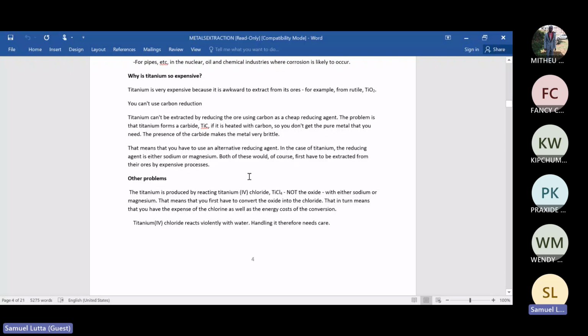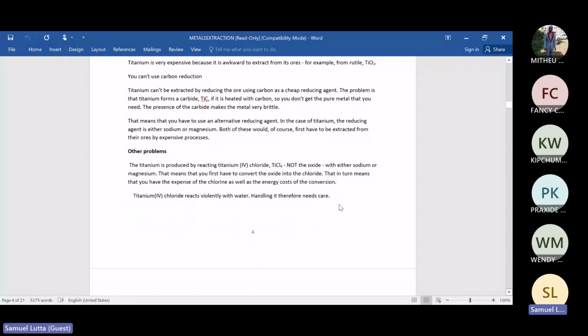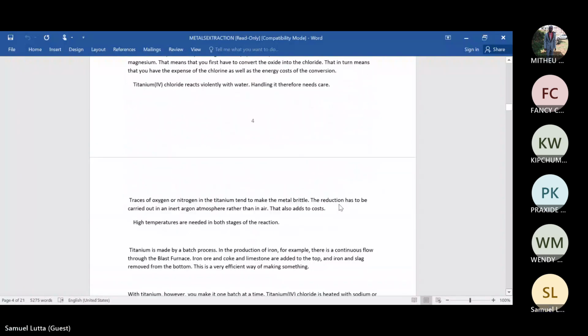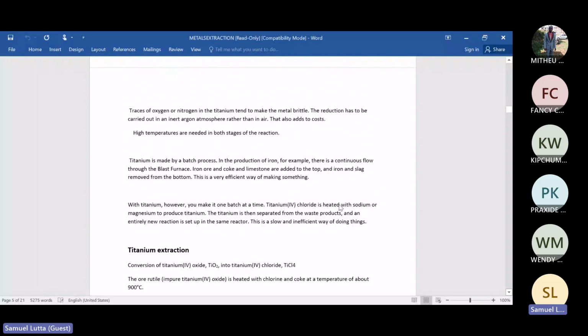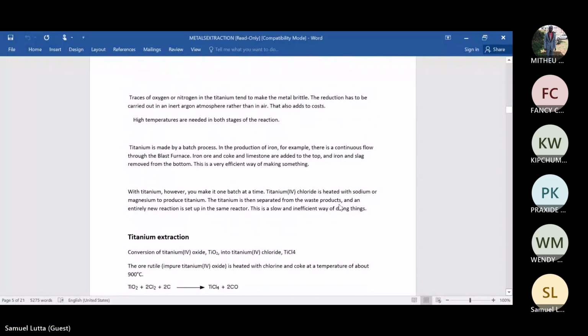So I think I've just said two reasons here. You can't reduce with carbon because titanium oxide will form titanium carbide. And then you cannot use titanium chloride as a starting material because this titanium chloride reacts violently with water. So to extract titanium, we need to use other processes and also special conditions.